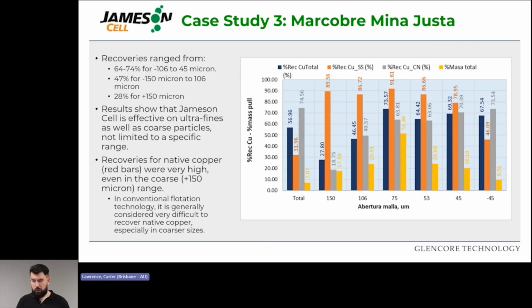Now, a little bit more of a deep dive in this size by recovery. So you can see from the 106 to 45 micron range, recoveries were 64 to 74%. 150 micron to 106, the recoveries were 47%. And for plus 150 micron, they were 28%. And this decrease was largely due to liberation.